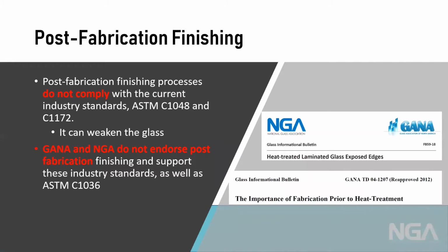So what about post-fabrication finishing? That's a situation where in many cases it does not comply with current industry standards, the C1048 and C1172. And as we mentioned earlier, it can weaken the glass. Once you start to alter the compression layer on glass that's already been heat treated, with heat strengthening or fully tempered, unless there's been testing that supports whatever the glass strength is after that process, it's pretty much an unknown.